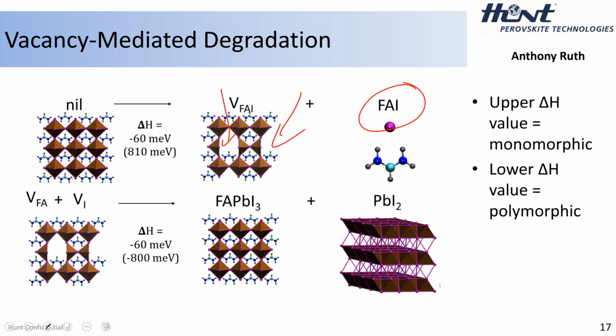So if it's a shallow trap, it falls in there with the conduction band, it probably won't cause a problem, right? You don't have mid-gap states that will act as charge traps. So who cares, right? Who cares if there's defects, because this material now is defect tolerant? Sure, energetically, but not structurally. Structurally, this is bad news. So it has to be addressed to make the material durable.